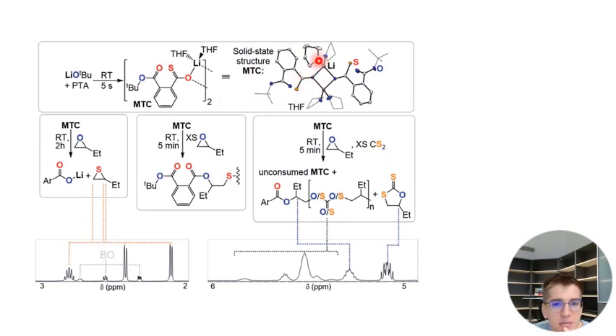This is how it crystallized. It formed this nice dimer, where importantly the lithium is not coordinated by the sulfur, and the sulfur sticks out. It's already nice, and we crystallized it from tetrahydrofuran as a model for epoxides. You cannot crystallize it from epoxides; they would just react with it. So I used THF, and it forms this nice dimeric arrangement, right? So now I took this species, did a stoichiometric reaction, reacted it with epoxide, and what you can identify are these thiiranes forming and the carboxylates forming. So this more or less proved this rearrangement reaction.